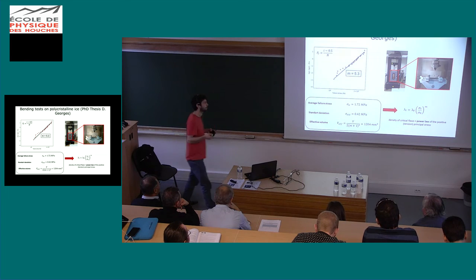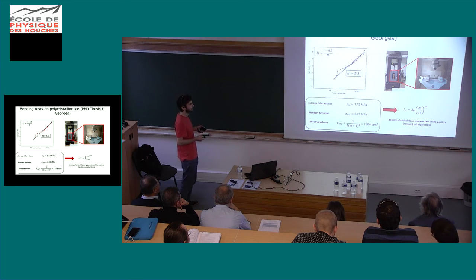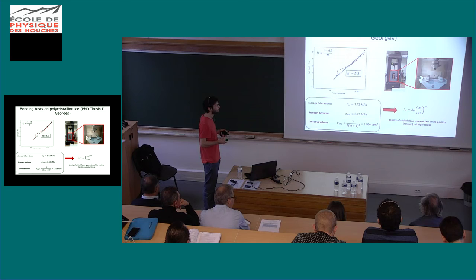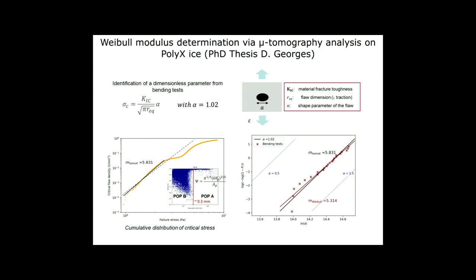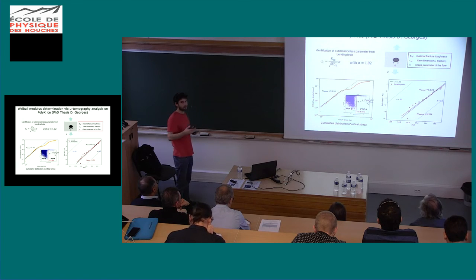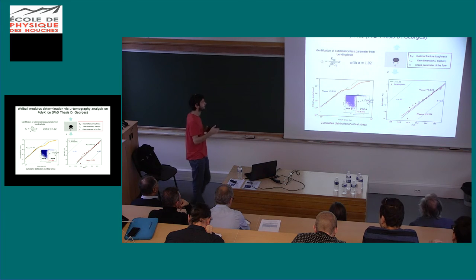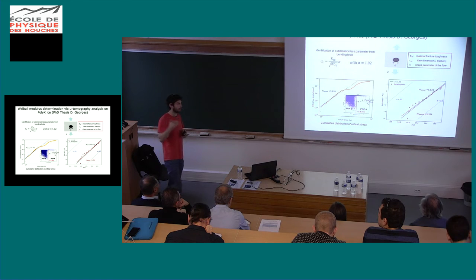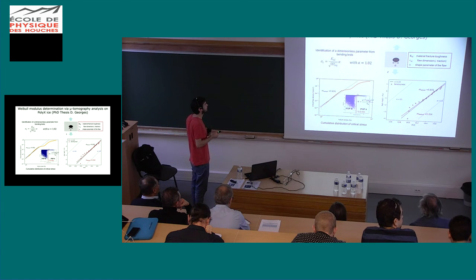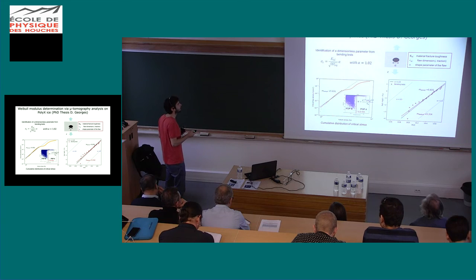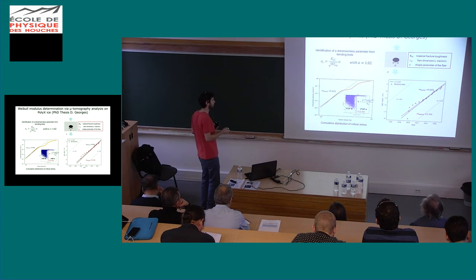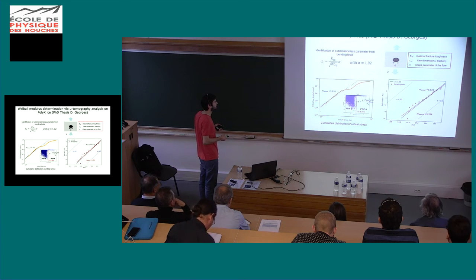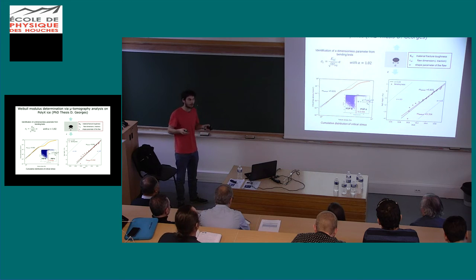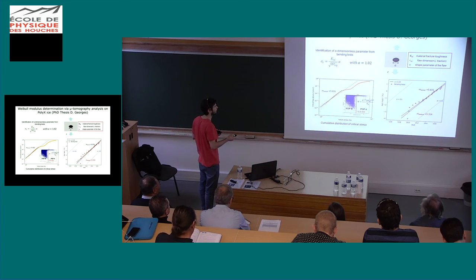And with these two Weibull parameters, we could compute a critical flaw density that follows a power law of a positive principal stress here. Also, as Maria said, it's possible to convert our bubble size distribution into a stress distribution by using linear elastic fracture mechanics theory. So we are converting the bubble size into a critical stress of activation. And for a given stress, we can determine the potential density of critical flaws in our material. It's the yellow curve that you can see on this graph.